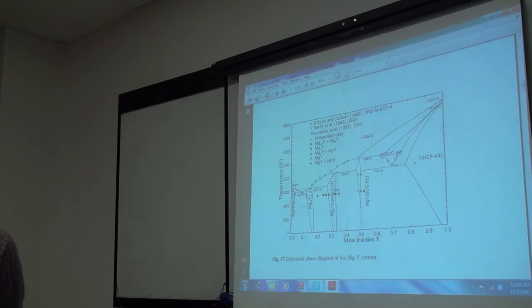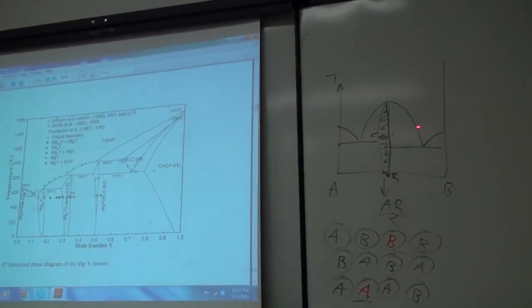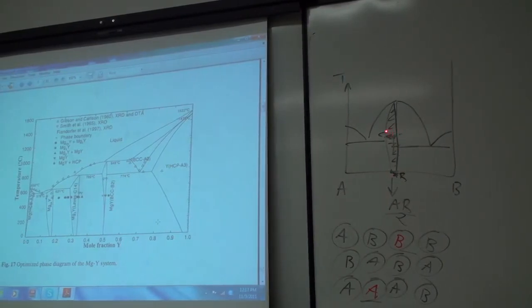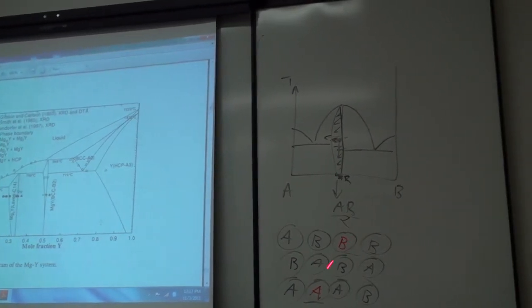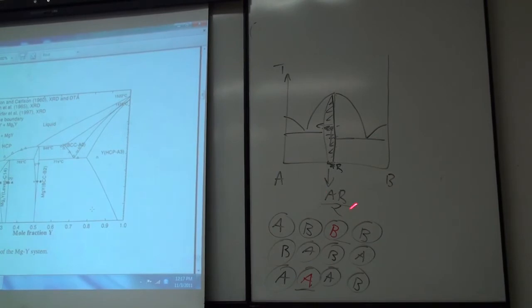As I said here, if you have quite a broad range of stoichiometry, a few percent, then at 50%, the 50% compound is not defect free. And now, of course, unlike the vacancies in the metal, you're not talking about 1 part in 100,000. You could be talking about percentages, so several percent could be defects. In that case, of course, the G naught of this hypothetical AB is nowhere near the G naught of real AB. It can be quite different.